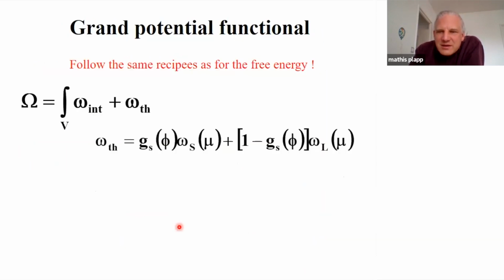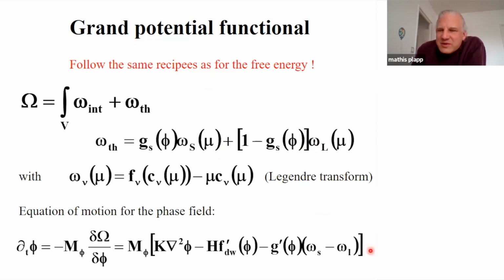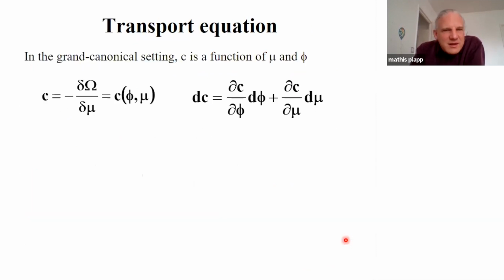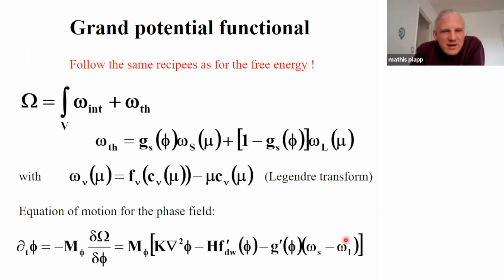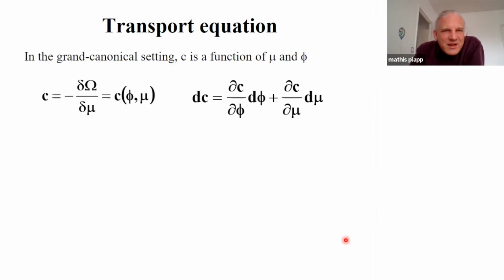That means in equilibrium, the driving force is zero, which is just the same thing as happened for the pure substance model with the temperature. So it's nice because in this way, we have achieved a complete decoupling between bulk and interface part, and we can fix the energetic parameter without hesitation.